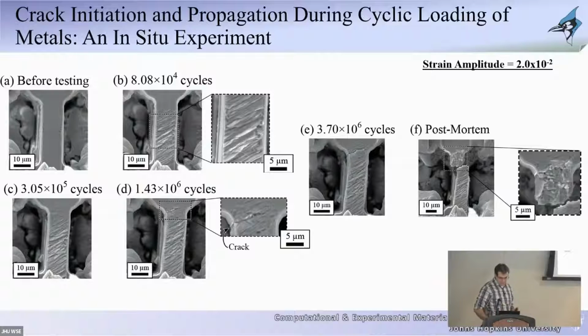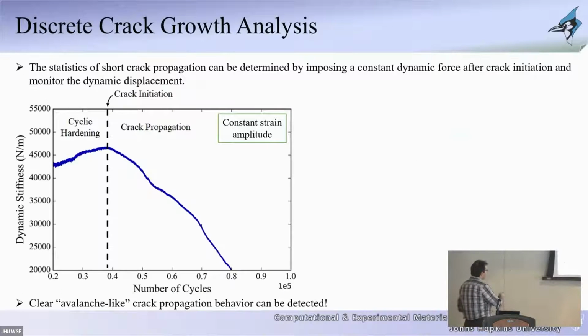So again, the same type of setup, same type of experiment. Now, if you look at the dynamic stiffness measurement, which I showed you before, and we're skipping up here to point to after we know that the crack, that big crack, initiated. And what you notice is that the dynamic stiffness had been continuously increasing, and then eventually a crack initiated. This is where we first observed that crack forming on the surface from an external observation. And eventually, as the crack continuously propagated, the stiffness started dropping, which is a common thing that you would observe.